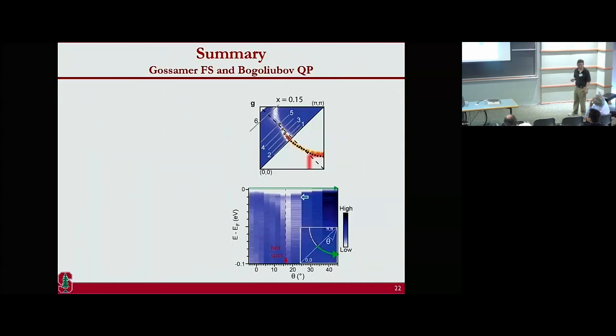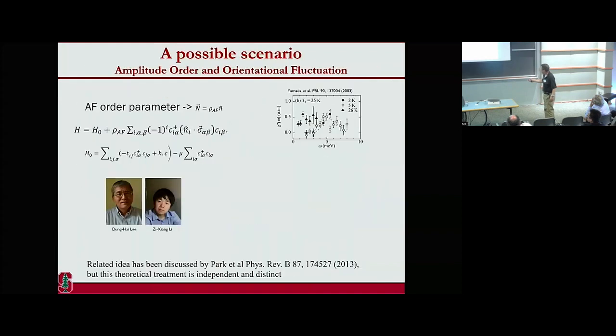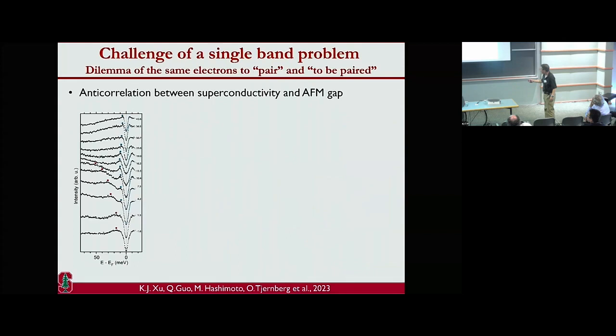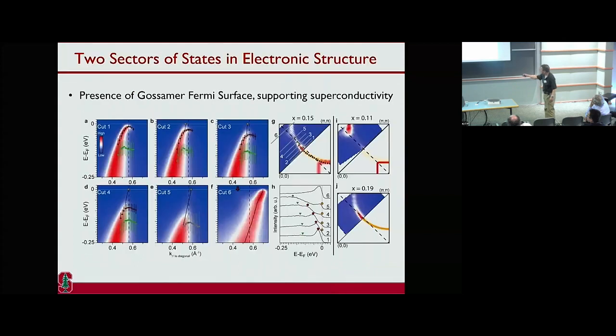Yes. I'm also confused about the same point Subir was. In the normal state, you think the Fermi surface looks like just the pockets around pi zero. There is a touch below the Fermi level, at least at this doping. So that plot there shows spectral weight there, but you don't think that's the leaking of the spectral weight? Because of a finite integration window, you will see signal leaking, but you can clearly see this.